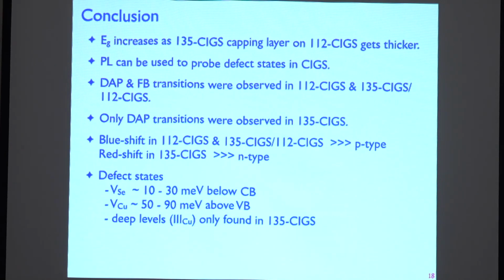So we can use the optical process to investigate the EG, and we found that the EG increases as the 135 thickness increases, or gets thicker, and PL can be used to probe the defect states in CIGS material. Donor to acceptor pair and free to bound transitions were observed in 112 and the 135 on 112 bilayer. And only DAP, donor to acceptor pair transitions, can be observed in only 135. The defect levels about 10 to 30 meV below the CB are designated for selenium vacancy in this material, and 50 to 90 meV above the valence band is for the copper vacancy. And as I showed before, the substitution of group 3 at the copper site is only found in the 135 material.